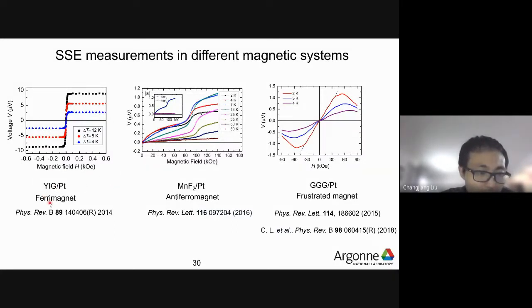For example, in ferrimagnet YIG/Pt system, and also in MnF2/Pt, which is here, this is an antiferromagnet insulator system. People can also measure a spin-Seebeck effect in some paramagnet, such as gadolinium gallium garnet or GGG. This is a paramagnetic material. It does not have a spontaneous magnetization or any Néel axis. Turns out that this is actually a frustrated material, and we found that this frustrated magnet at low temperature can show very unusual response of the spin current, which could be a probe of the short range ordering in the frustrated magnetic system.